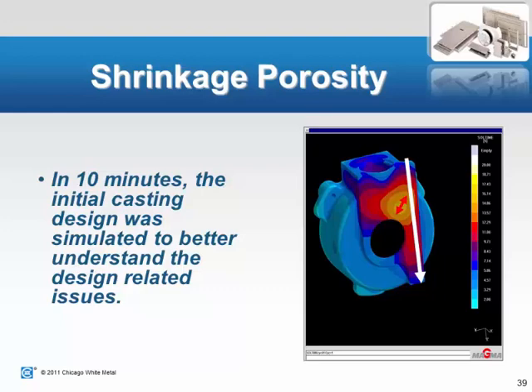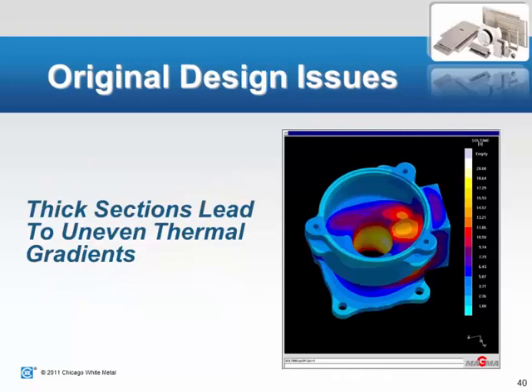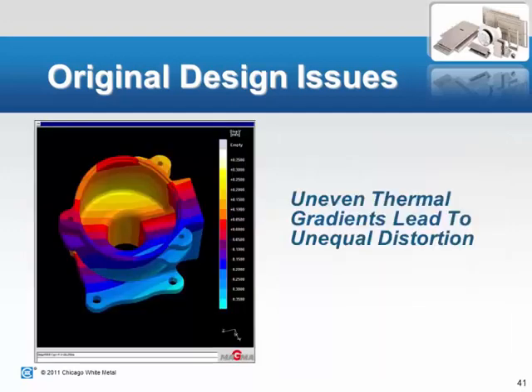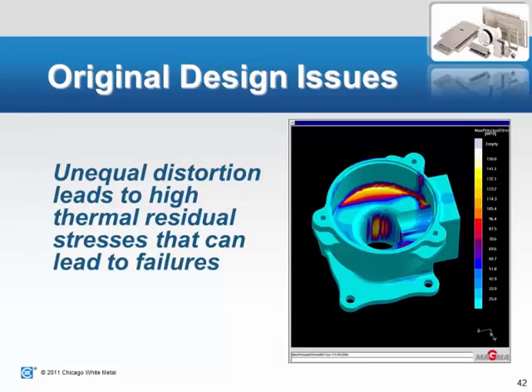Another view of the part from above, and you can see again the thermal gradients that are in there based on the thick wall sections. The uneven thermal gradients lead to distortion. And then that distortion can lead to stresses that are remaining in the part after it comes out.